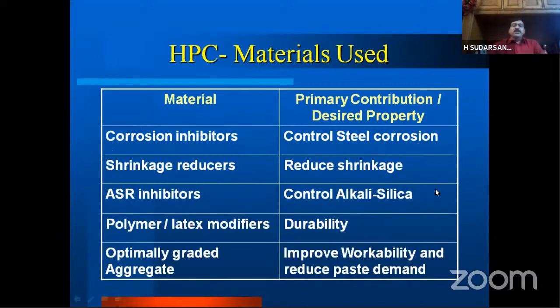We have corrosion inhibitors. You know, if you are constructing a structure under aggressive conditions, corrosion is a great destructor. So to prevent the corrosion, we have corrosion inhibitors, shrinkage reducers, ASR inhibitors to reduce the alkali silica reactions, polymer and latex modifiers to obtain the durability, and the graded aggregates to improve the workability and reduce the paste demand.